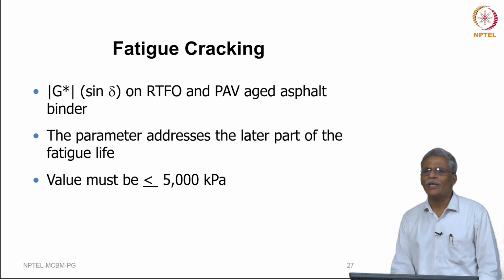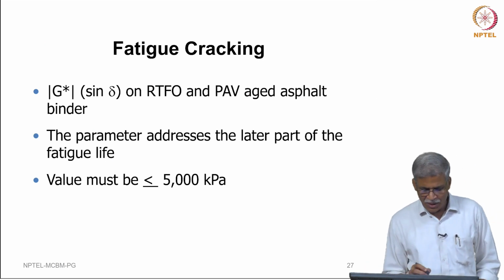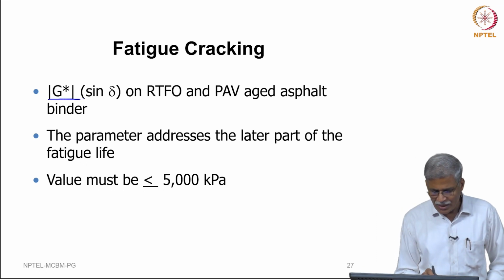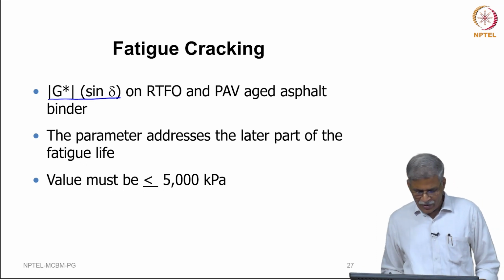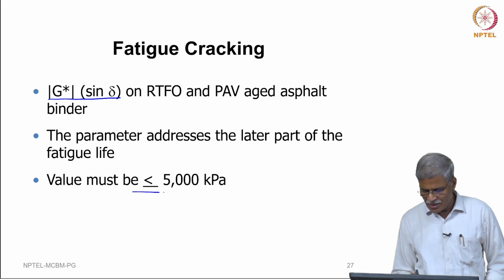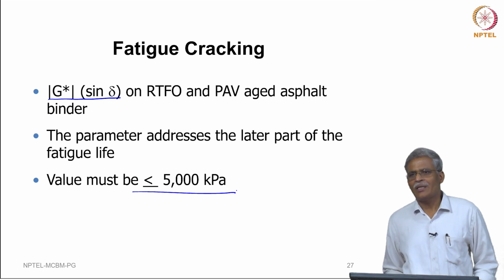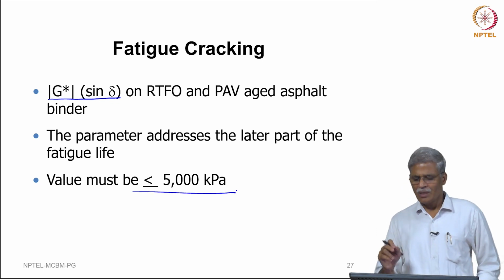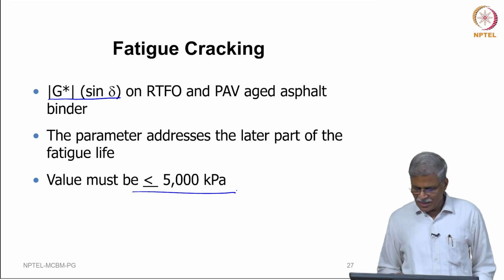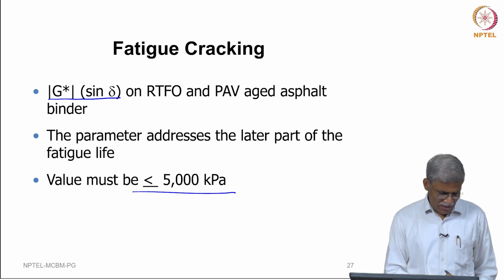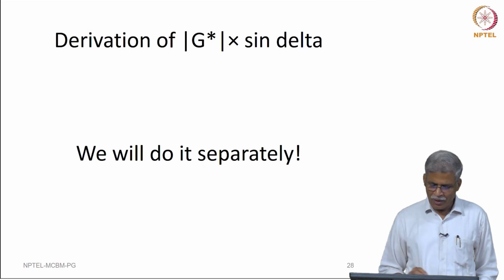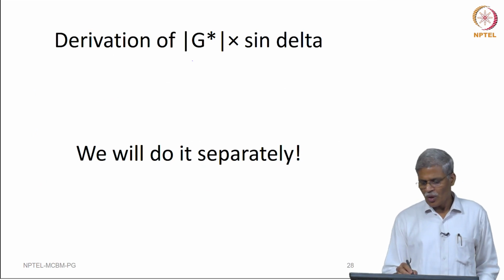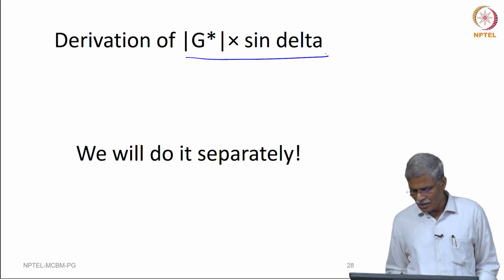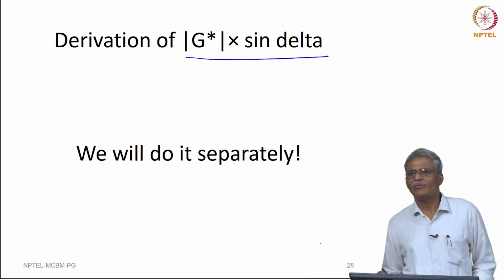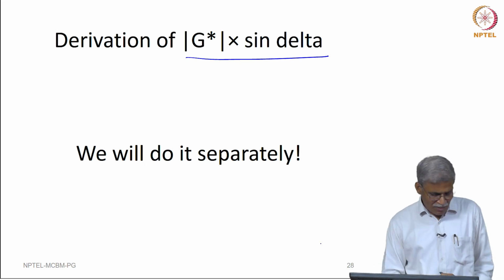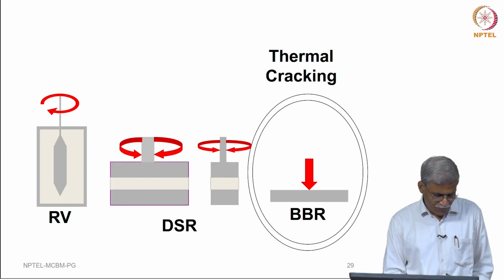And what we do here after this aging is find out the G star sine delta value, and this is prescribed as less than or equal to 5000 kilopascal. Now, what exactly is the reasoning behind this, we will discuss as we go along, okay. The derivation of what G star times sine delta is and what it has to do with the fatigue damage will be done by me separately, okay.